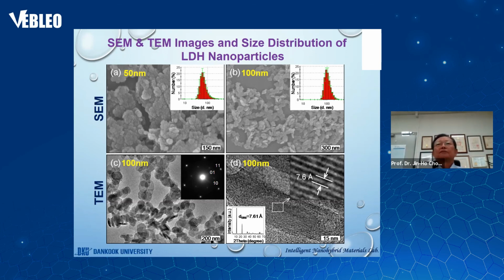After washing and freeze drying, the APS grafted LDH was dispersed in deionized water, and FITC ethanol solution was then added. And then the mixture was stirred vigorously at 37 degrees C for 12 hours. The LDH-FITC thus prepared was collected by centrifugation, washed with water and ethanol solution, and then freeze dried.